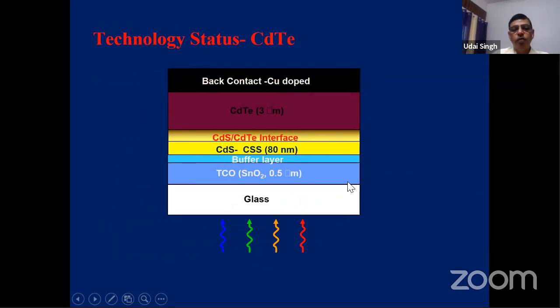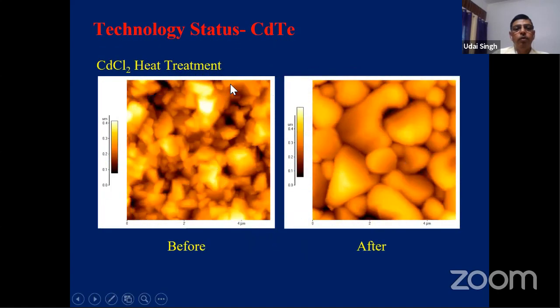Structure wise, you have glass, a transparent conducting oxide, a buffer layer, and then this cadmium telluride. Due to intermixing, some interface is formed between the cadmium sulfide and cadmium telluride, and then the back contact. People have slightly tried copper. So light goes this way. One of the advantages here was that earlier, when you deposit the cadmium telluride, you have this structure.